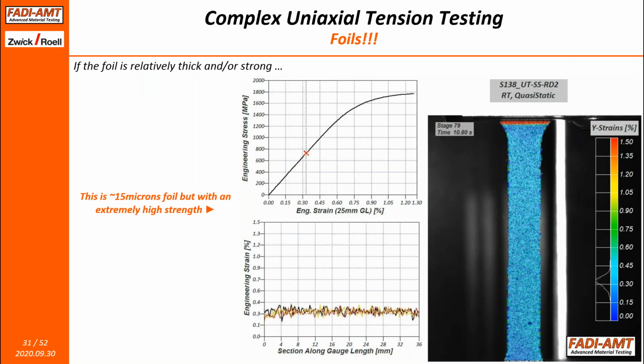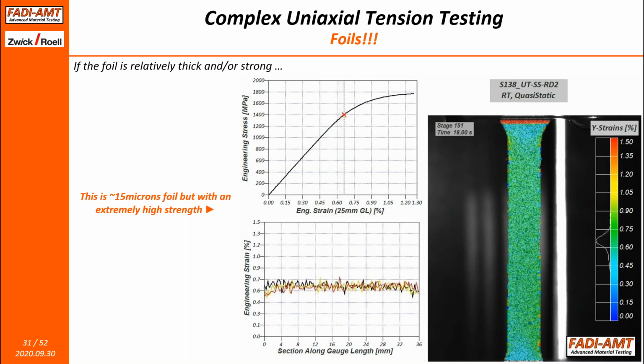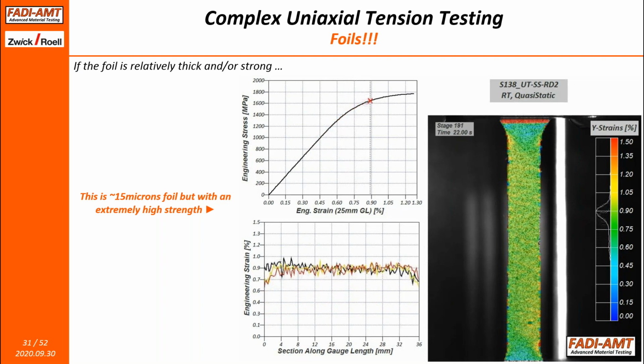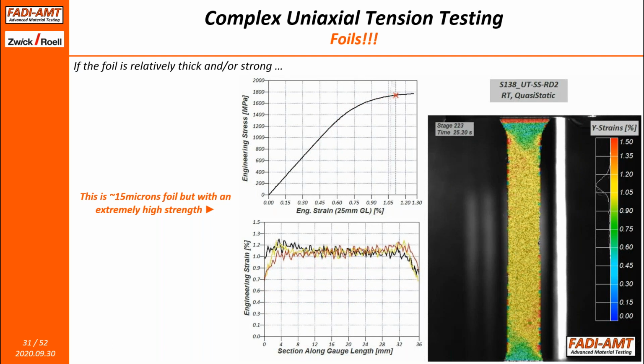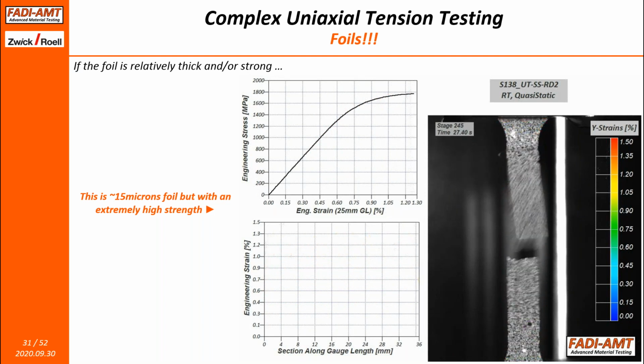I'm going to give you a couple of examples where either technology would work. If you have thin foils, but the strength of the foil is very high, then it is technically not a significant problem. You can use laser extensometers and video extensometers, so long as you can provide marks on the sample for the system to track, and you should be absolutely fine. It's not a big problem with thin, high-strength foils because your likelihood of damaging the sample is lower.